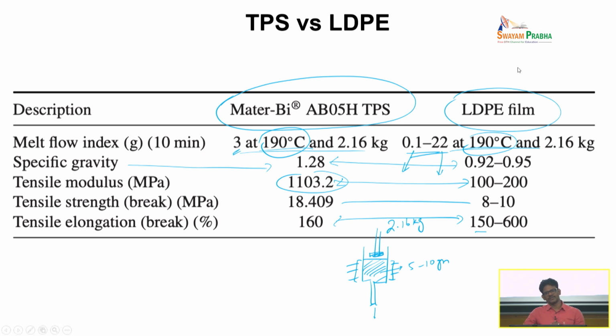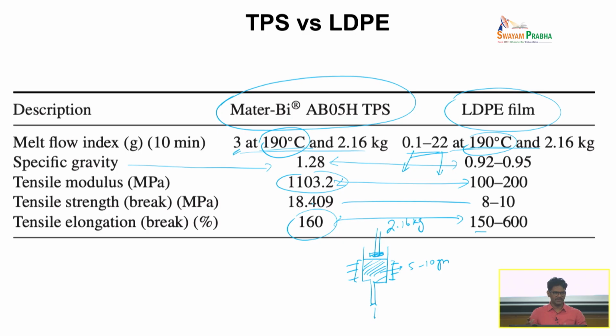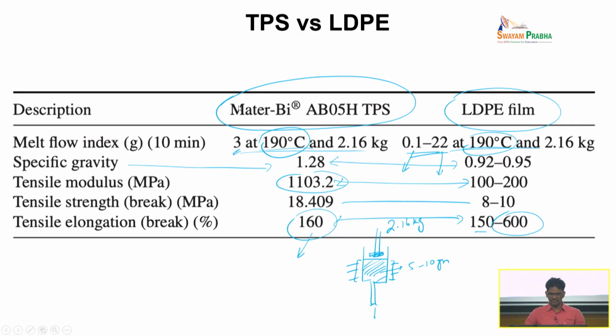But then there are some other applications where the film will be put into some very high speed roller mills. Okay, so in that case you want a very high elongation at break. Okay, in that case this may not be a suitable one. It may just tear in high speed roller machines at high shear. So this one having about 600% means you can actually extend it 600% of its original length before it actually tears. Okay, whereas this one you can only increase by 160%, then it will tear. So that means this polymer is a little bit more brittle and it breaks. Okay. But in other conditions you can see that they are broadly comparable except the elongation at break.